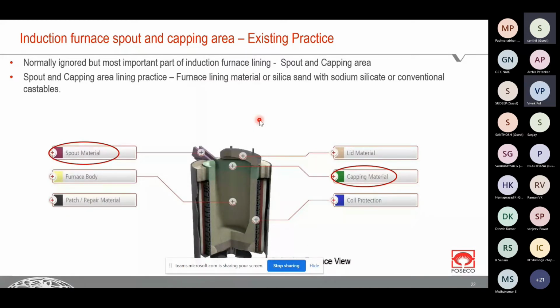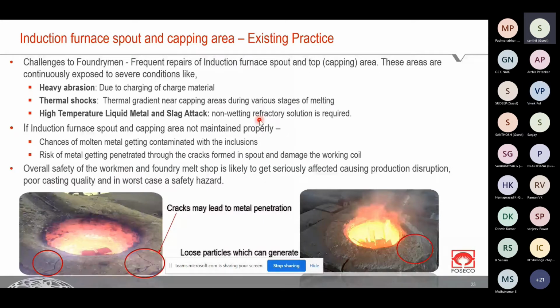We can use silica sand or some castable, but all these products are not designed for those applications of spout and top lining. Why? Because the spout and top are exposed to severe conditions like heavy abrasion, thermal shocks, and slag attacks, and that's why there is always a tendency to form cracks and inclusions. Through these cracks, the chances of metal penetration are very high. As a result, there are very costly runouts, and safety is also compromised. So that is the risk associated with it.